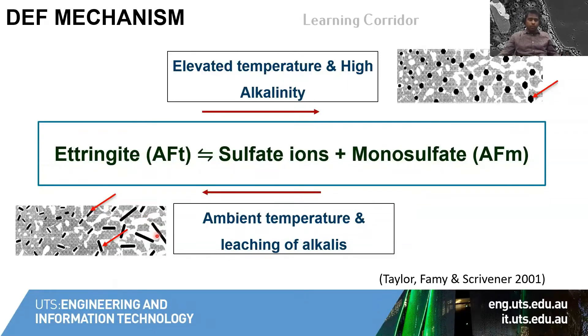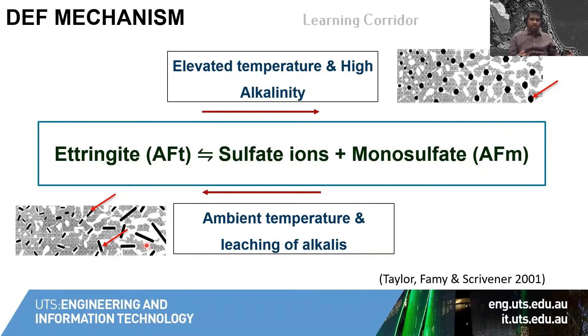This ettringite precipitation is actually happening in a hardened concrete already in service, so there is no enough room for the ettringite to get precipitated. Also, ettringite is a large volume-occupying hydrate — the professor would actually show you a lot of expansion graphs in the external sulfate attack section — which basically says that when ettringite forms in a hardened system in laboratory specimens it will expand because it's an unrestrained environment. Whereas in real-life concrete, any volume-occupying hydrates forming in a hardened environment will lead to cracks.